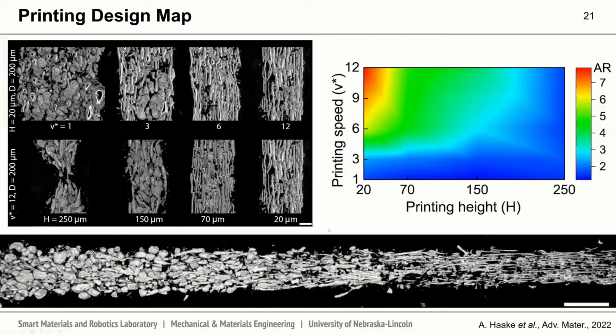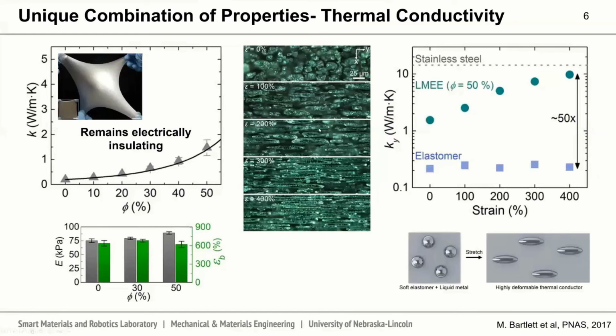I guess another question: rough estimate of the range of orthotropic thermal conductivity ratios. Do you have a rough estimate? I had a graph in here, but it looks like I didn't include it. We see a pretty significant increase in the direction of strain of the thermal conductivity. In the perpendicular direction, in X and Z, we see almost a negligible change in thermal conductivity. We see almost no decrease. While very slightly, it remains almost nearly constant.